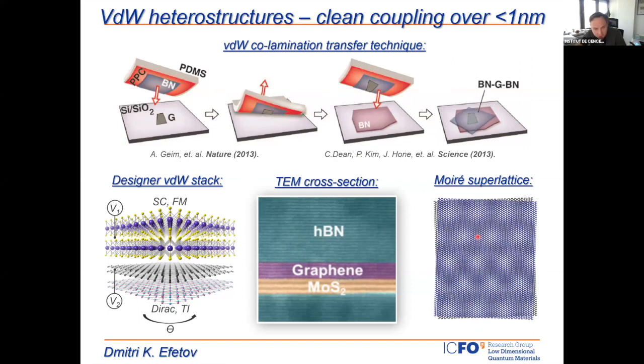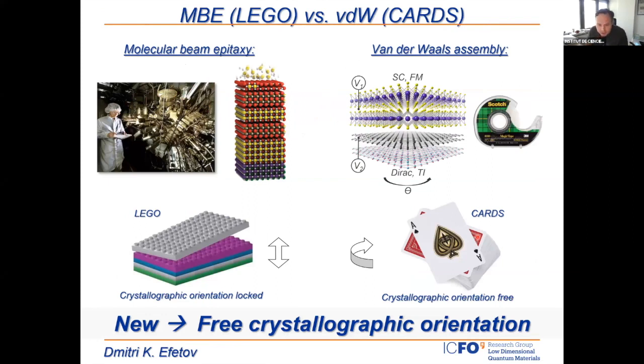I want to contrast these heterostructures made from van der Waals materials with heterostructures that were traditionally grown over the years and decades before. The difference is that we do not start with single atom species which we sprinkle onto substrates, as in molecular beam epitaxy. Because you start with single atoms, you guarantee that when these atoms hit a particular surface, they align to the crystallographic orientation of that surface. So you cannot choose the crystallographic orientation; they all point in the same direction.